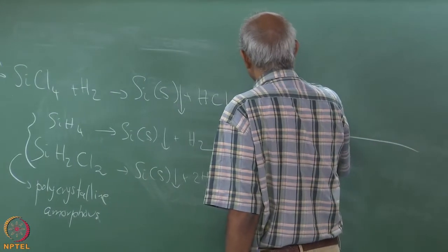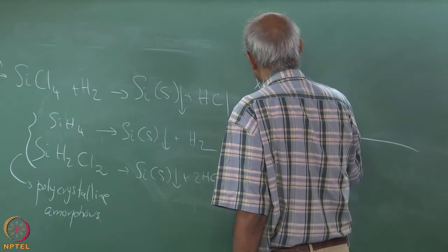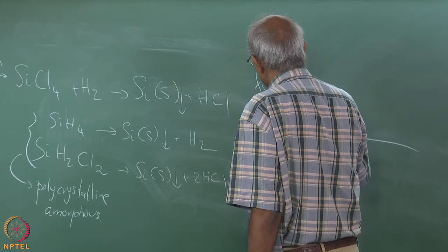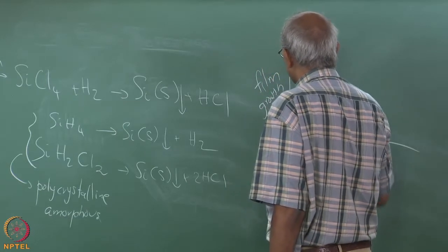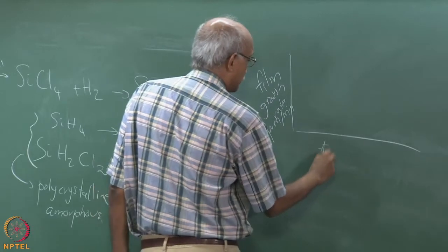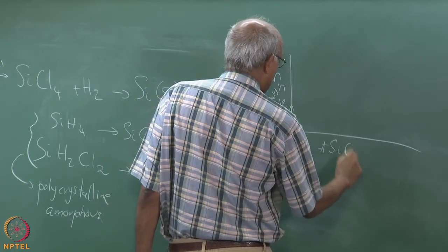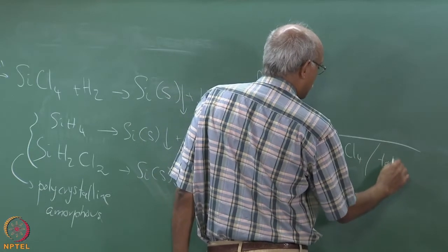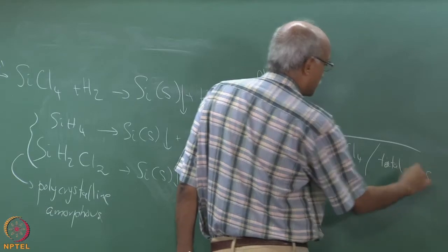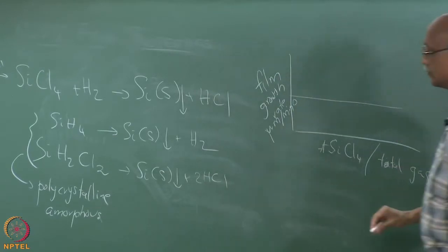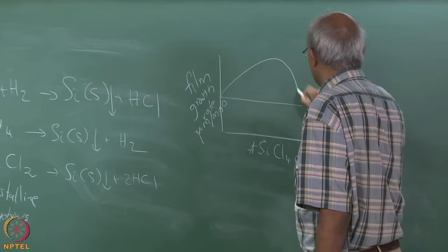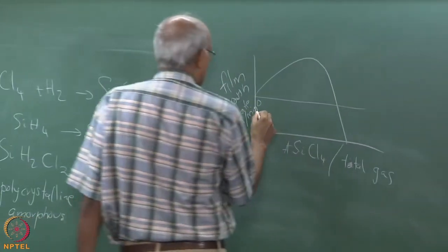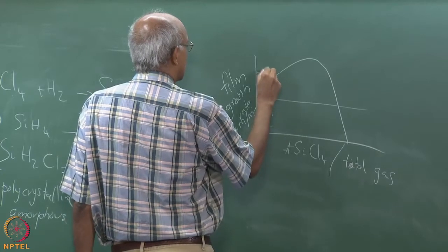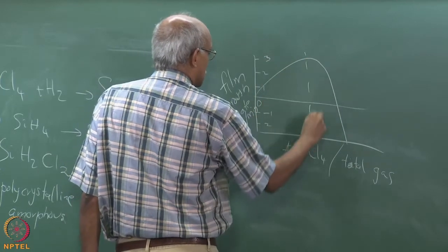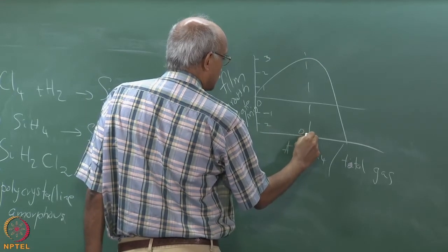In fact, if you plot the film growth rate, which is typically in micrometers per minute, against the number of SiCl4 molecules as a fraction of total gas molecules, you can actually have a behavior where the deposition rate goes from positive to negative. In fact, the typical behavior looks like this. So, this is minus 1, minus 2, 1, 2, 3. This is somewhere around 0.3.